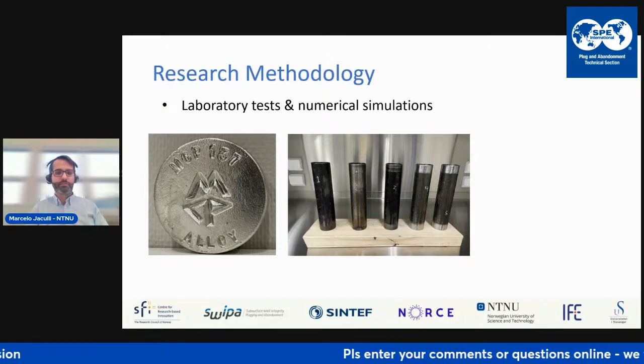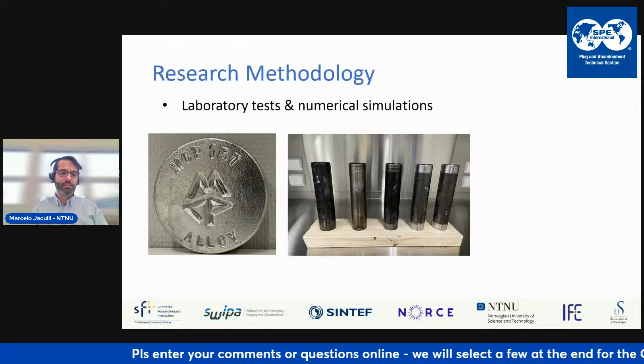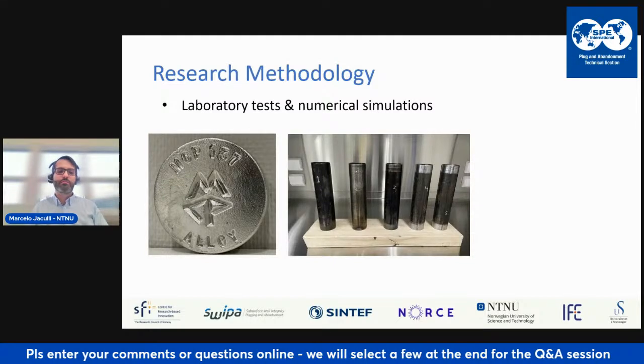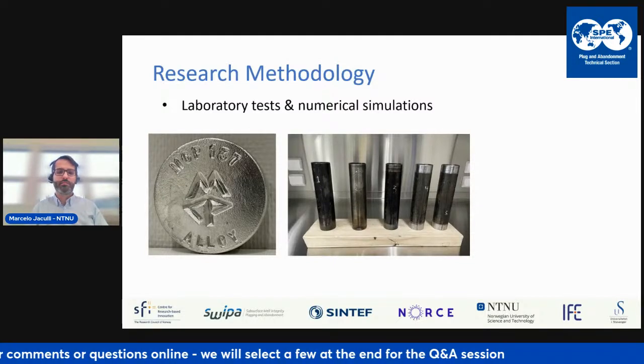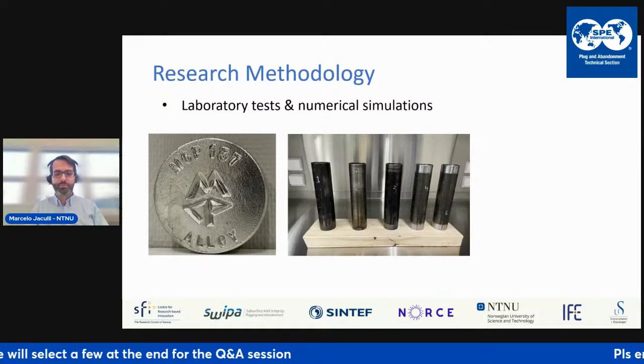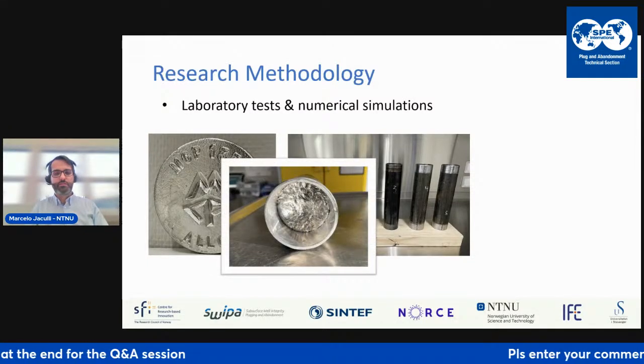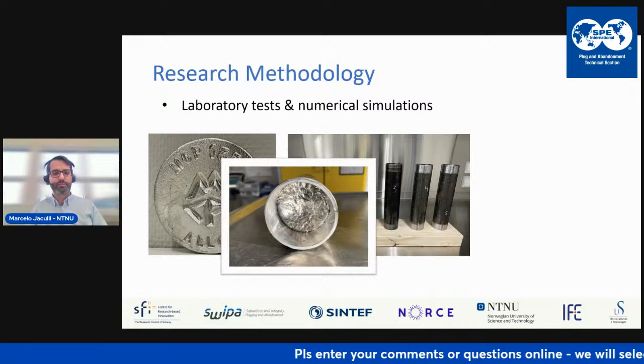On the left side, you can see a sample of a bismuth tin eutectic alloy. We just take this and pour the liquid alloy into one of these pipes. After it solidifies, it forms this nice plug inside the pipe, and then we take this for testing.